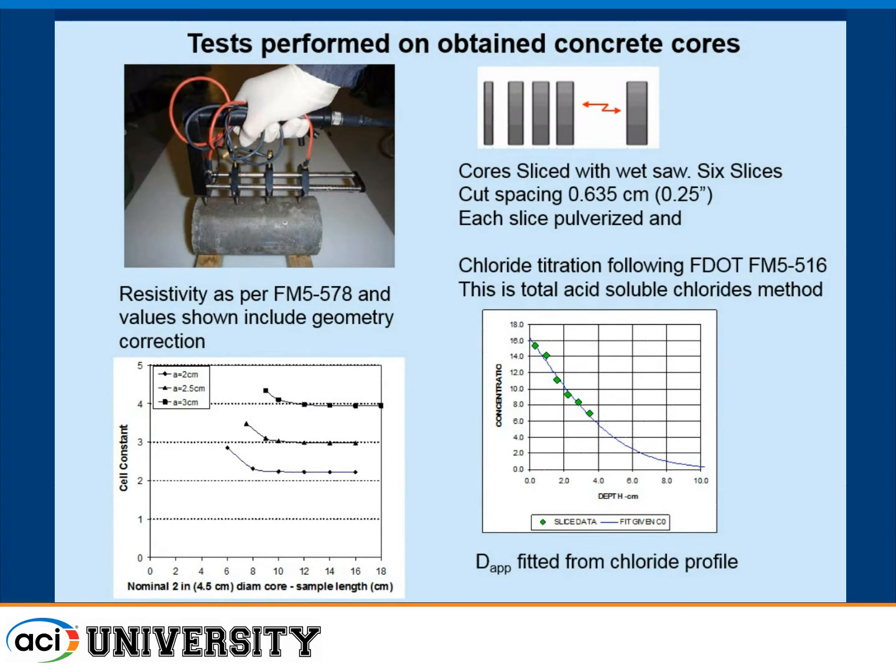Although that particular specification we didn't modify, our cores, as you remember I mentioned, were either 12.5 or 15 centimeters in height, and this specification called for a 3.8 centimeter spacing. You cannot do it. So fortunately, we were using this type of probe where you can adjust the spacing, and we did it with either 2 or 2.5 centimeter spacing.